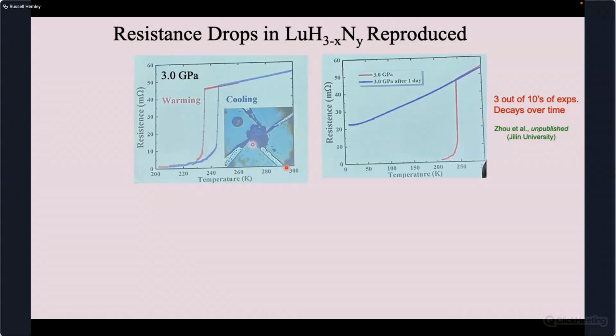You can see this resistance drop on warming and cooling at quite high temperatures. The problem is, and this is what plagues the field for this system, and that we see over and over again in our experiments, is you tend to see a decay of this behavior over time. So after multiple runs, the samples deteriorate, and that's one of the challenges in reproducing this. In fact, most of the samples don't show these resistance drops, but show something else. But there's still something quite interesting buried in this.